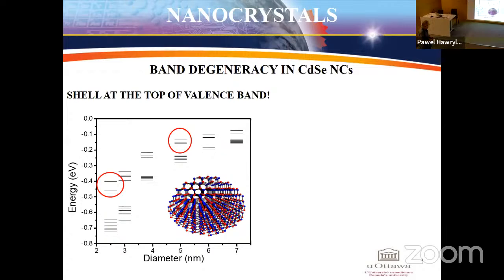So if you take a cadmium selenide nanocrystal for different diameters, you will find that I am showing the one-electron energy levels, and it turns out that the top of the valence band is not just one level that you like to think, a 1s level or a hole. No, it is a band of states. It is a band of states, or a shell of states, at the top of the valence band.